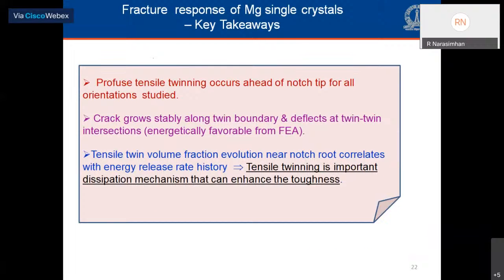Now let me summarize the key takeaways from this part of our work. We noticed profuse tensile twinning occurring ahead of the notch tip in all the orientations which we studied. But the pattern of twin development depends on the lattice orientation, as we saw in the difference between orientation A and orientation C. In all the experiments, the crack is seen to grow stably along the twin boundary, getting deflected at twin-twin intersections, which we showed from our finite element analysis to be favorable from the standpoint of energy release rate. Perhaps the most important takeaway is the fact that tensile twinning is an important dissipation mechanism. Its evolution near the notch root correlates well with the energy release rate history. So that establishes that this is to be considered as a mechanism that can enhance the toughness. And we will see more of it in the polycrystal experimental work, which I'm going to show next.